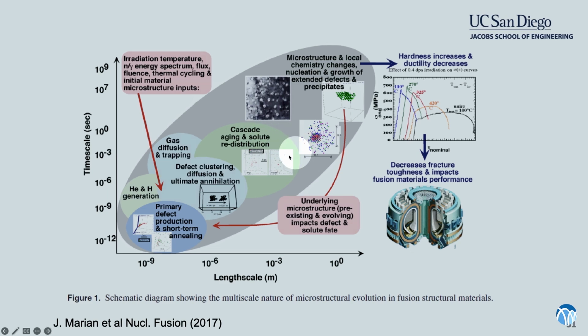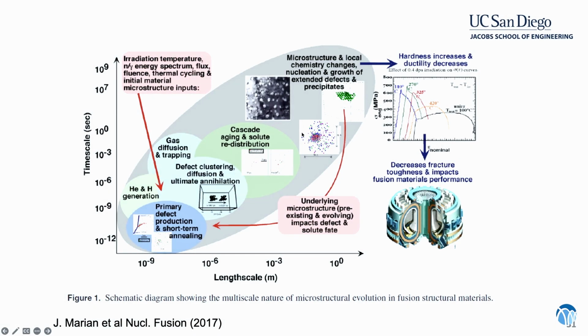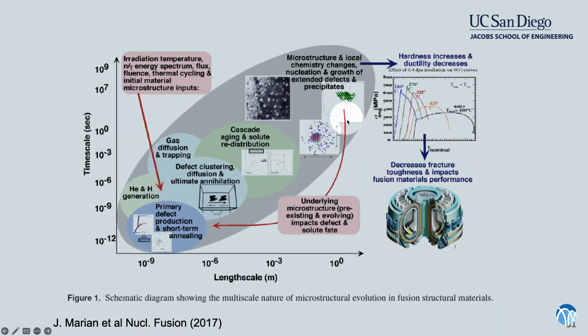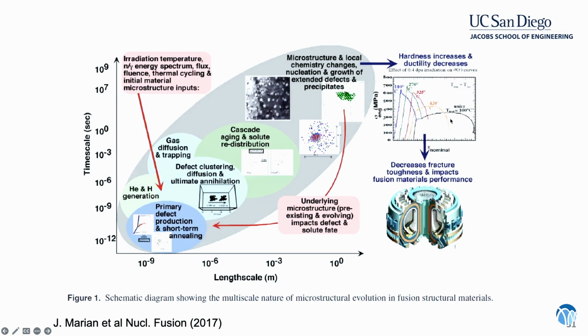So for example, and I'll show you some other micrographs of this, you can have void formation. You can have diffusion and major microstructural changes. And of course, what happens when you do that is that the material you started with is no longer the material that you engineered to start with. So one thing that can really happen is that the material becomes brittle, and the fracture toughness goes way down, and now your material will break when you don't need it to. And of course, that breaks your device.